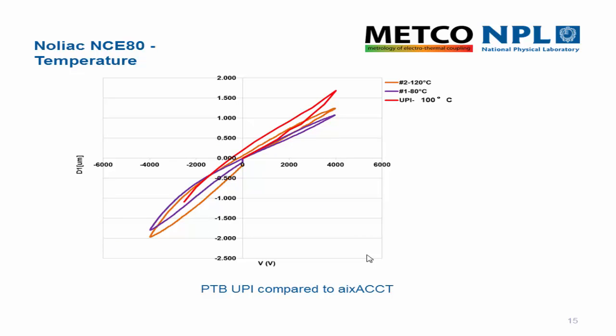This is a comparison between the measurements at PTB and the aixACCT system, and you can see that the PTB measurements, this red curve up here, is showing much bigger displacement at 100 degrees C than measurements on the aixACCT system at 80 or 120. So this seemed to be quite an anomaly, and the trend's not going in the right way either.